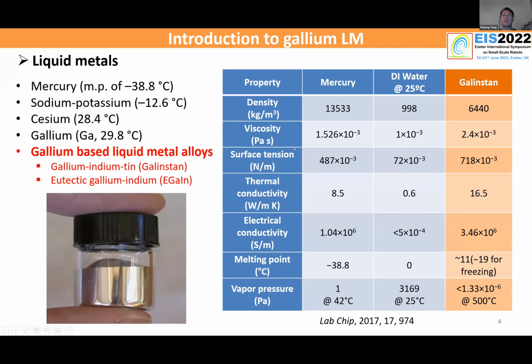I made this table to briefly compare some physical properties between mercury, DI water, and one of the liquid metals we use, gallium. As you can see, the density of gallium is half that of mercury, but it's still about 6.5 times that of water. They all share very similar viscosity, but gallium has much higher surface tension than water, approximately 10 times. As a metal, it has high thermal and electrical conductivities. It has a melting point around 11 degrees, below room temperature, so it's liquid at room temperature. But it's not going to freeze until you cool it down to around -19 degrees because of the supercooling effect. Also, it has almost negligible vapor pressure compared to mercury, making it much safer to use in a laboratory or in our daily life. And gallium, indium, and tin are not as toxic as mercury.